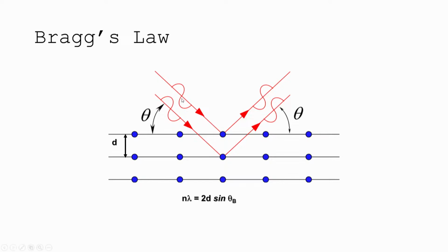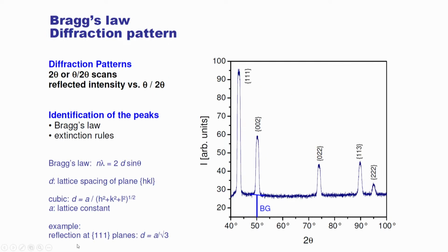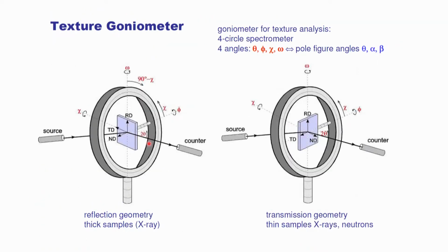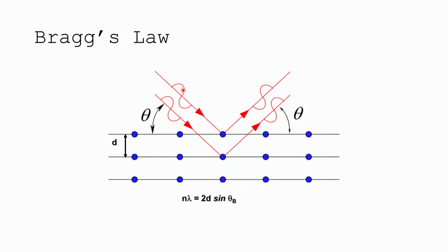So we have the wavelength of the incident radiation coming in here, right? We have the wavelength, lambda. We have the diffracting angle, which is the incident angle with the diffracting planes. So here's a set of diffracting planes. D is the interplanar spacing between those planes. So this is dependent on what HKL is. So D, a lot of times, will have the subscript HKL. So we have the radiation coming in, we have the radiation that's diffracted, and it's diffracted only at that specific angle theta, which is defined here, defined in the equation.